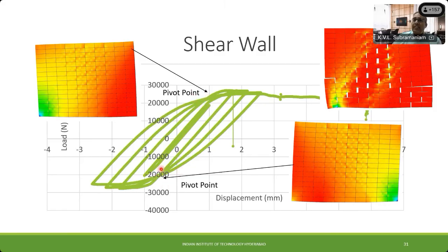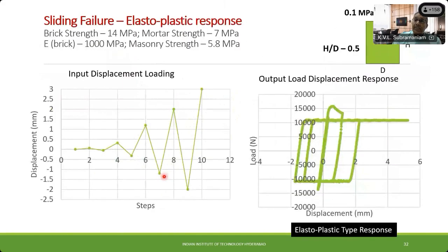Experimentally also, data that's available had a pivoting type of response for walls which failed in shear. Then the walls that failed at sliding, which are squat walls with very low levels of compression, the kind of failure that we get looks like an elastoplastic kind of response. The reason I'm even bringing this up is because at some point we'd like to be able to do parametric analysis where I can parameterize these, and then I should be able to run simulations for different types of walls.